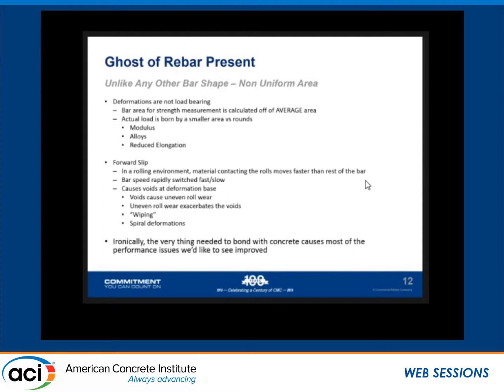You also have a phenomenon called forward slip. I'll explain it a little bit more on the next slide, but what happens when you're rolling, the steel near the roll moves forward through the mill faster than the steel in the middle. And this creates its own issues. It creates little tiny voids in the steel, especially at the bottom of the deformation. It causes uneven roll wear because of the deformations. You get a pattern called wiping at the bottom, and again, I'll explain that wiping on the next slide.